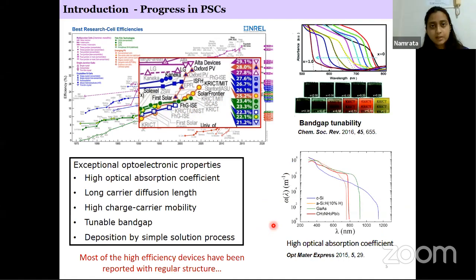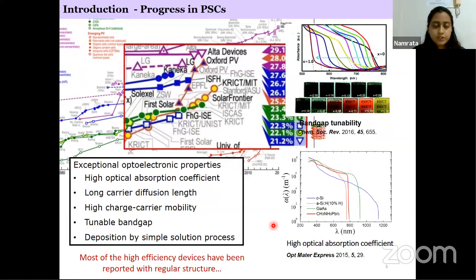So the progress in the perovskite solar cell power conversion efficiencies has been quite remarkable. As we can see from the figure at the topmost corner on the left side, this is the famous chart from the National Renewable Energy Lab, and it shows that perovskite solar cells have seen an accelerating growth. It has reached an efficiency of 25.2% in less than a decade. And this is remarkable, I emphasize again, because we are now at the same standard as silicon solar cells. Silicon solar cells have existed in the market for more than 50 years, and to reach that level in less than 10 years is quite an achievement.